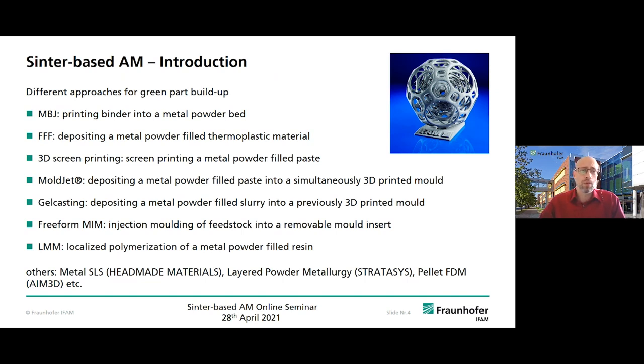Mold jet is a very similar process, but it does not make use of screens, but you basically build up the mold of a wax-like material layer by layer and just spread the paste into these spaces that you leave out. Gel casting is using previously 3D printed molds, which are then filled with a metal powder filled slurry. And a very interesting process I will come to later is the freeform metal injection molding, I call it here. So it's combining injection or MIM with removable mold inserts that are also 3D printed.